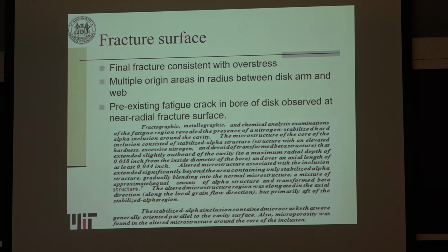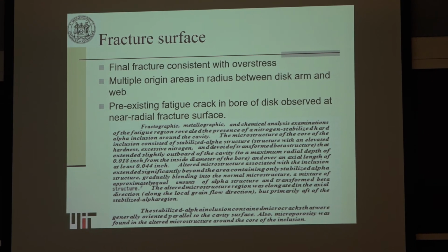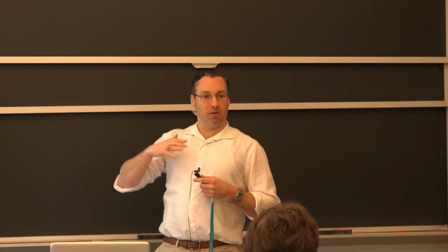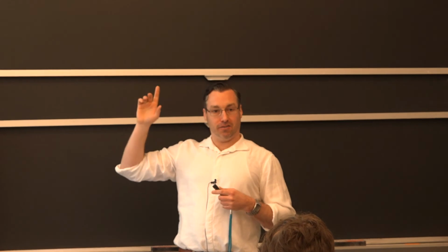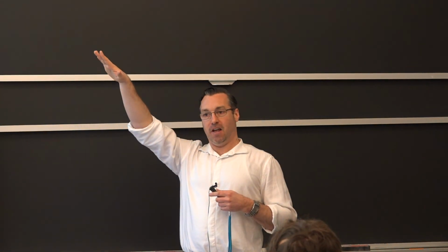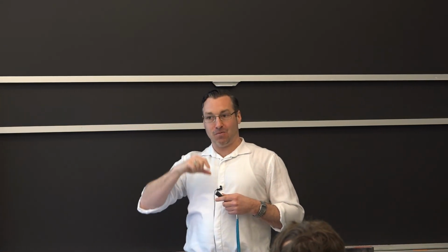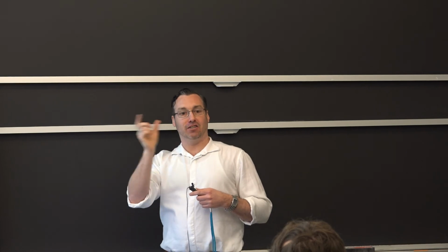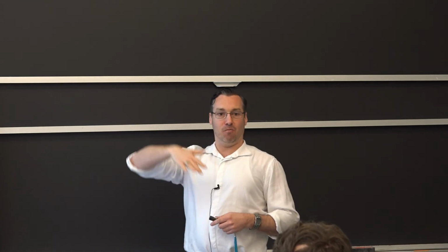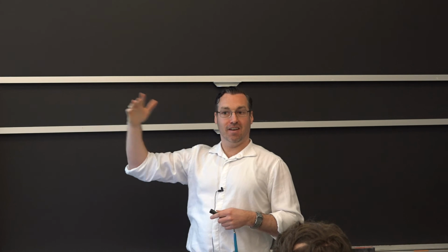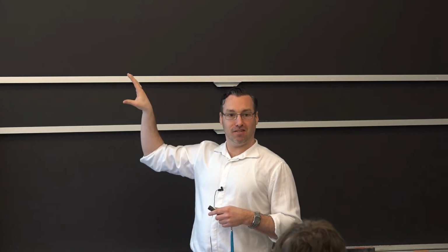The key thing is that since it was from an inclusion from the manufacturing process, the NTSB report finds that the crack initiated from the first cycle, the virgin flight of the plane, on the very first cycle. And it went through multiple inspections where this was missed.